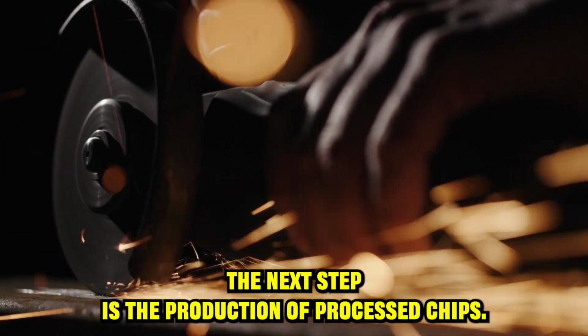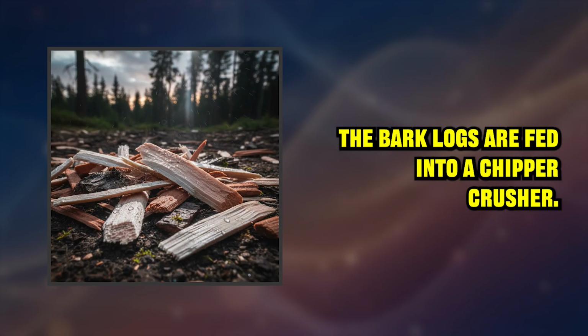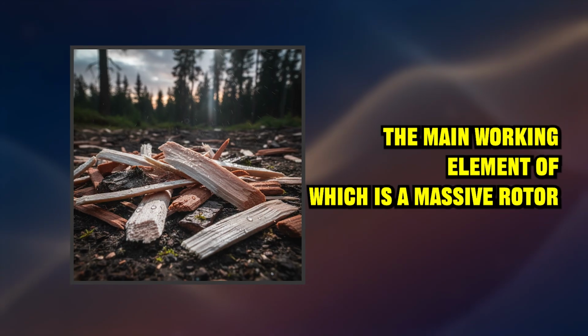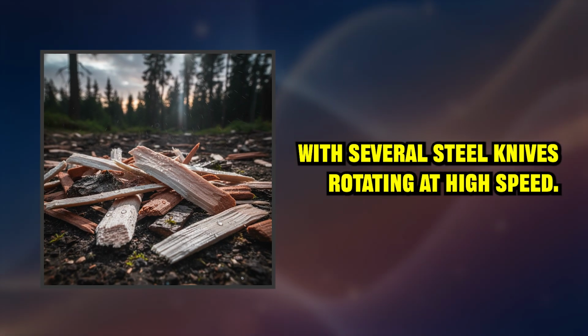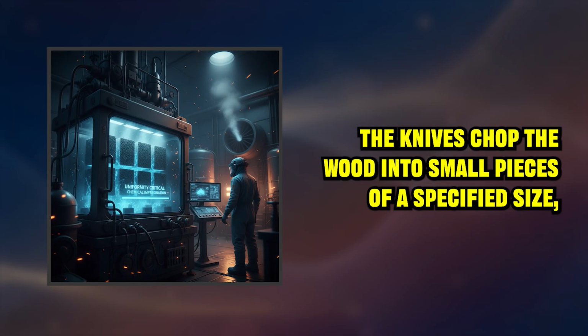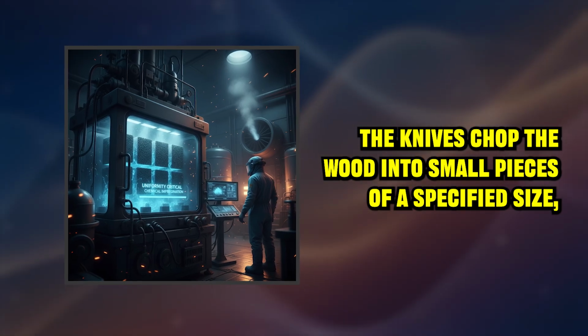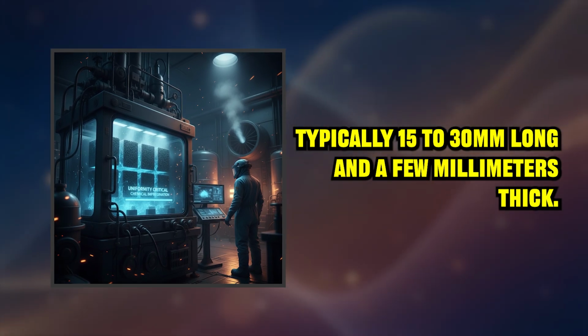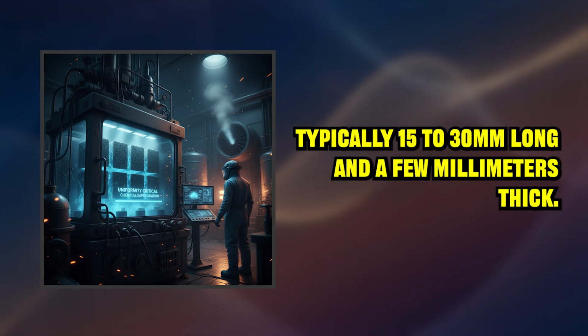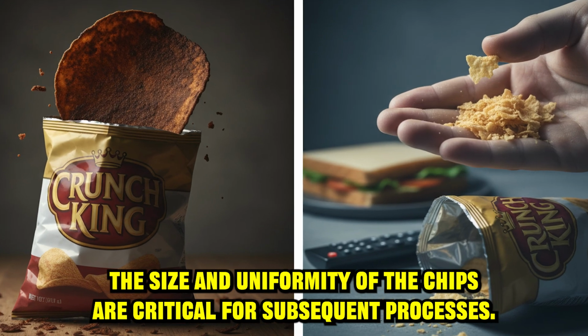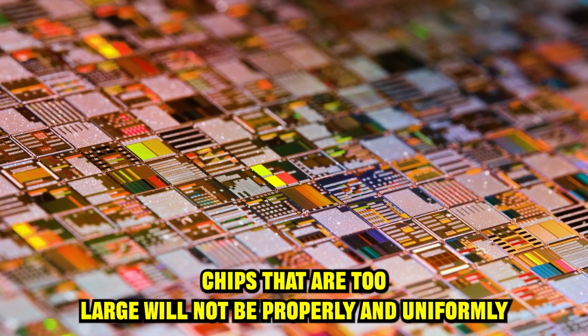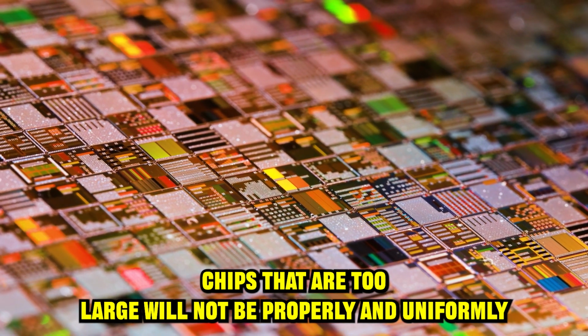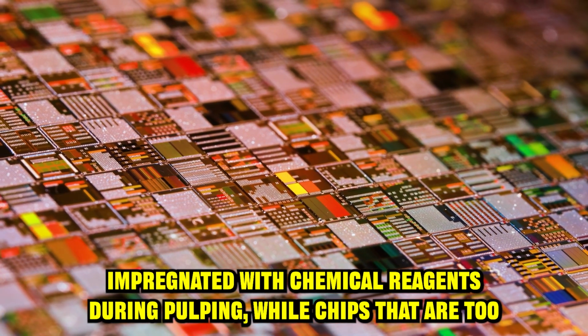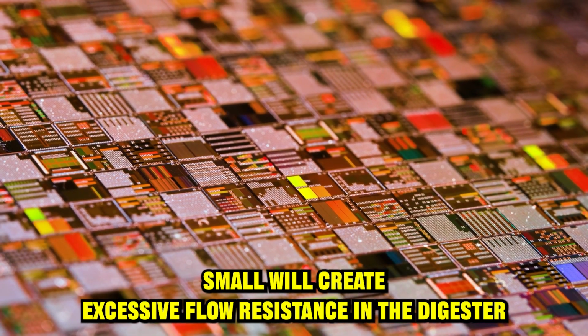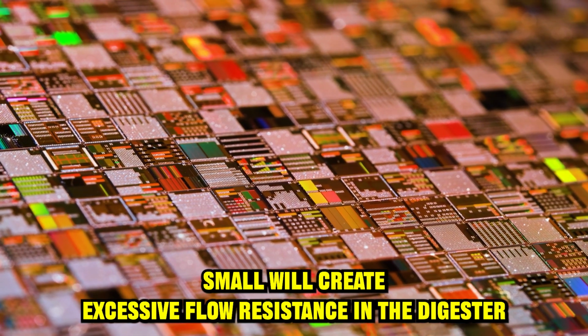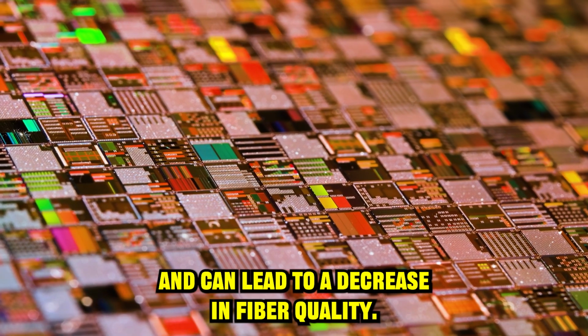The next step is the production of process chips. Debarked logs are fed into a chipper crusher, the main working element of which is a massive rotor with several steel knives. Rotating at high speed, the knives chop the wood into small pieces of a specified size, typically 15 to 30 millimeters long and a few millimeters thick. The size and uniformity of the chips are critical for subsequent processes. Chips that are too large will not be properly and uniformly impregnated with chemical reagents during pulping, while chips that are too small will create excessive flow resistance in the digester and can lead to a decrease in fiber quality.